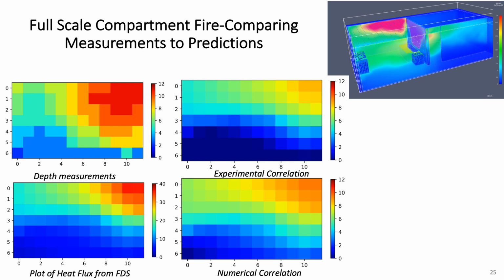The last step was analyzing whether or not the numerical model and the correlations fit a full scale experimental series, like a practical application of it. We compared a full scale compartment fire test, and you see in the top right corner a diagram, essentially fire starting in a sofa along the right back wall. We are comparing the depth measurements on that wall to a plot developed from Fire Dynamics Simulator.